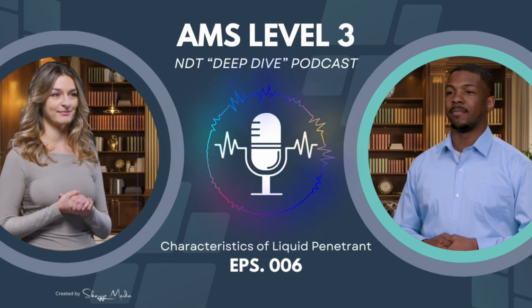So the developer breaks that trap. Precisely. The developer particles coating the penetrant seepage provide countless tiny, randomly oriented surfaces. When the trapped light hits these particles, it reflects and refracts in all directions. This allows nearly all of that previously trapped light to escape the film and travel towards the inspector. And that's where the huge brightness increase comes from. That's where that potential 8-fold or even more increase in apparent brightness comes from. It's unlocking the trapped light.